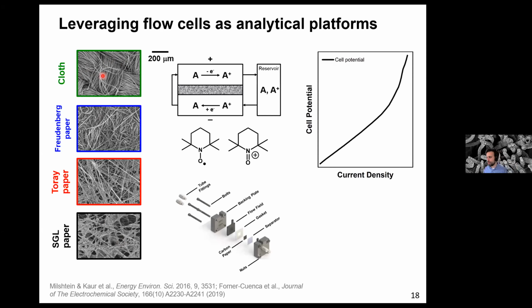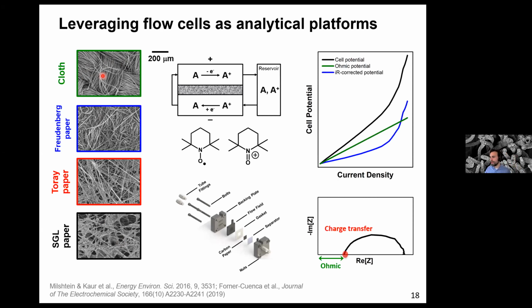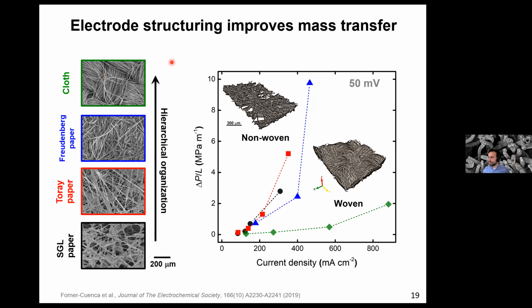And we've used model platforms to try to deconvolute what is the role of mass transfer. So we want to know the mass transfer overpotential as a function of the material type, okay? And by doing that, we realized something really interesting, is that all these non-woven electrodes, they kind of collapse through the same trend line that gives you moderate current density, and they take quite a lot of pressure drop to pump the liquid through. However, when you move to these woven materials, these are very well-organized materials with aligned channels, with large pores and small pores, so bimodal pore size distribution, you get the best of both worlds. So you get very high current densities at the fixed overpotential, and you also get low pressure drop.